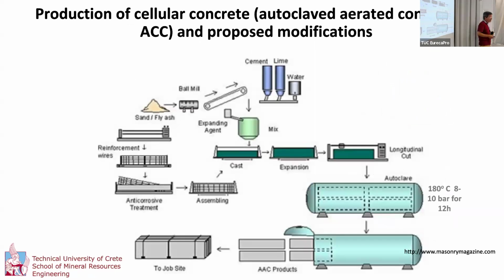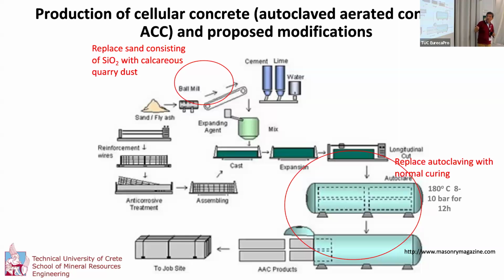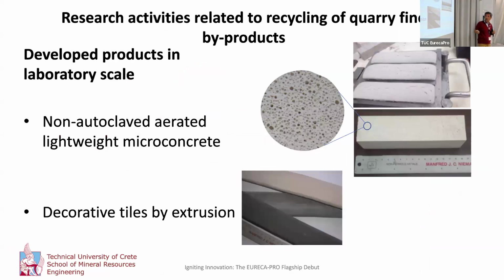On this, I will show you the idea. The lightweight microconcrete is a substitute for very well-known commercial products such as autoclaved aerated concrete. You know the firm Ytong or something similar to this one. So the idea here is that we studied how this material is produced, and we found that we can substitute the silica sand used to produce it with this fine material from quarry waste, and also substitute the autoclaving procedure with normal curing. This means that with this modification we have a low energy consumption process, and we have produced at laboratory scale this material you see here with these pores. We are at the moment working on developing prototypes on a larger scale.